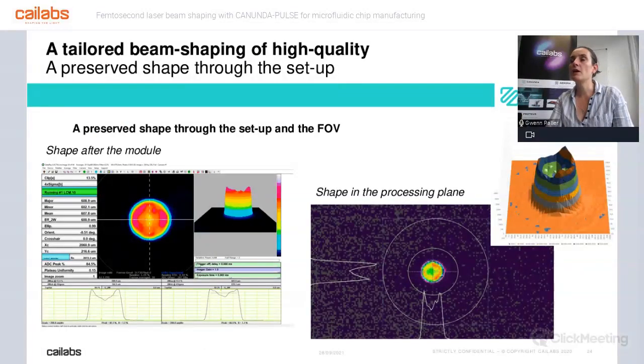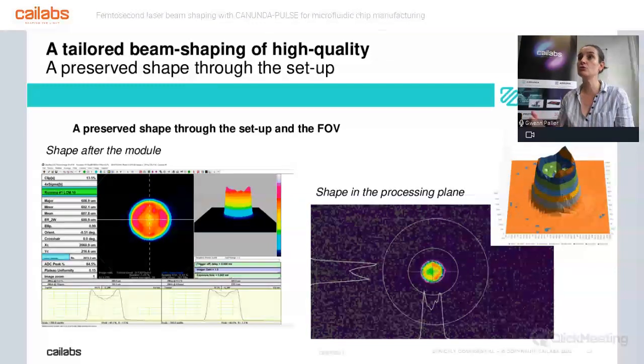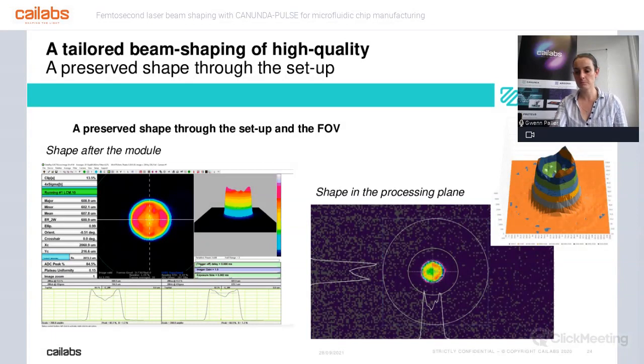What is important to say when you say that you have a high quality shaping is that you preserve the shape. Having a nice shape just after your module somehow is not very complicated. What is very important is to preserve this shape through the setup, so through the scanner, through the F-theta lens, and over the whole field of view of the F-theta lens. If you are using, for example, diffractive optical elements, DOEs, it's based on diffraction, as the name says. And most of the time, you will have distorted output beams inside the field of view when you are at the edge of the field of view. In our case, as you can see on the left, you have the U shape at the output of the module, and you manage to have the same U shape 10 times smaller in the processing plane.